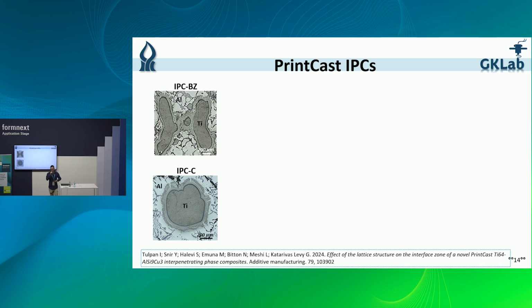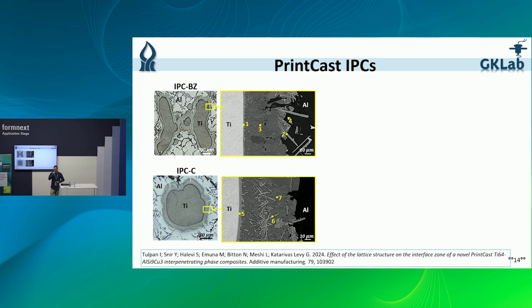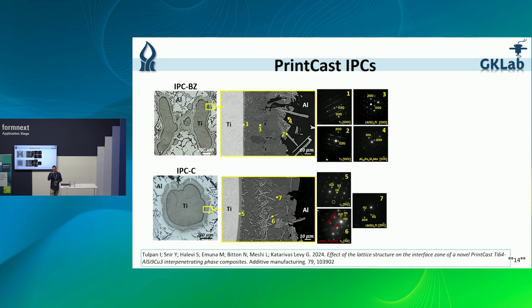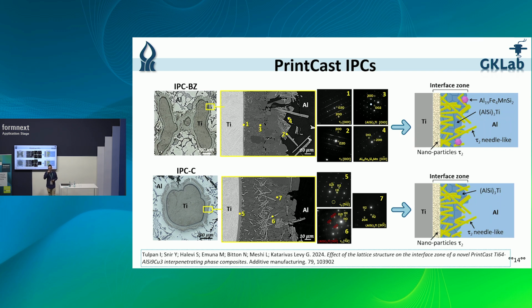Here we can see sections of the IPCs that we produce, and we can see scanning electron microscope images of the titanium lattice on one hand and of the aluminum matrix on the other hand. And we can see that an interface layer had formed in between the two materials, which allows the aluminum to bond to the titanium lattice. We investigated the phases that make up this interface zone using electron diffraction, and we identified a variety of different intermetallic phases that formed during the cooling process.